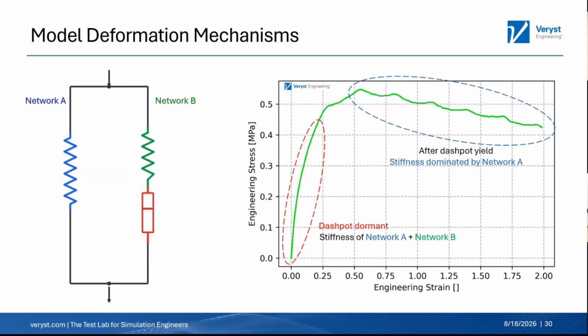If you work with these models long enough, you'll see that at that small strain range, up to 10, 15%, you're not going to see a difference in any of the rates, and everything's going to be right on top of each other. But then we get a shift in the curve at, say, 25 to 50% strain, where it's much softer. That portion there that I've circled in blue is when the dash pot has yielded. That's why I like to call it a viscoplastic response. We're getting a lot of deformation there. And what that means is that we really just have the stiffness in network A. As we pull on this, all our forces are going into network A. We have a very low force response due to that dash pot. So we get a much softer response.